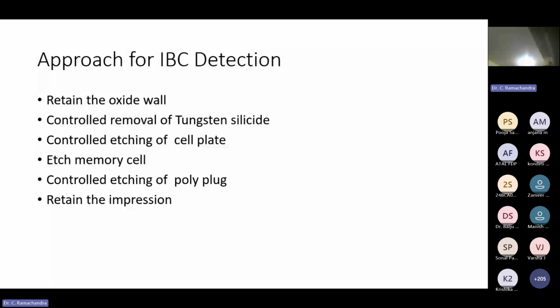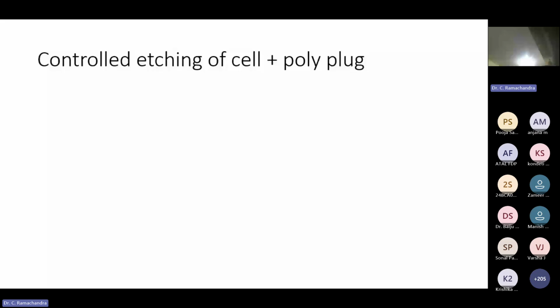So it requires controlled etching of the memory cell, controlled etching of the polyplug. I have done a lot of calculation and come to the conclusion that in my system, I have to use as low power as possible. It was a 600 watt RIE system we had, but when I went below 40 watt, the plasma started triggering, flickering, so it is not stable. Therefore, I cannot go below 40 watt. I found that at around 60 watt, I get low and stable RF power.